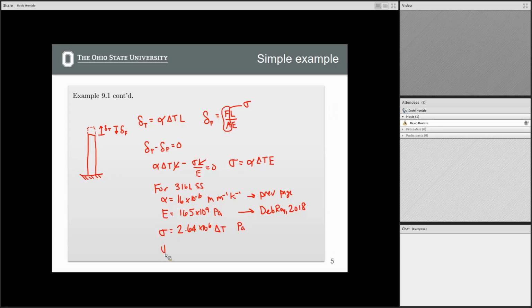Keep in mind, this is from the Debroy paper as well, that the yield stress for 316L stainless steel is going to be equal to 435 times 10 to the 6 pascals. Okay, so I can look at these here and say, what can the temperature difference be before I start to yield this material? You can look at this and say, these are both 10 to the 6. Somewhere around or a little less than 200 degrees centigrade or Kelvin, which, compared to the type of temperatures that we're using with additive manufacturing processes, is really not that high. That's a pretty small temperature.